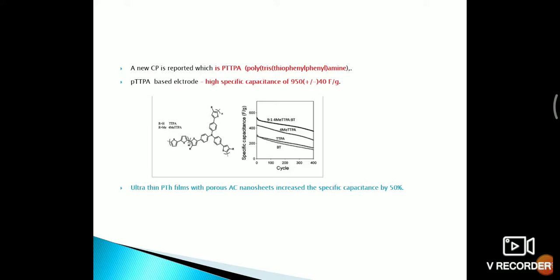A new conducting polymer is reported, which is PTTPA, polytristhiophene phenylamine. This PTTPA based electrode shows high specific capacitance of 950 plus or minus 40 farad per gram. And the specific capacitance per cycle and cycle stability is shown in this graph. We can see that the pure TTPA showed a lower specific capacitance, whereas a combination of PMET and PTTPA shows a higher specific capacitance and a higher cycle stability. Besides this, ultra-thin polythiophene films with a porous activated carbon nanosheet increase the specific capacitance by 50%.